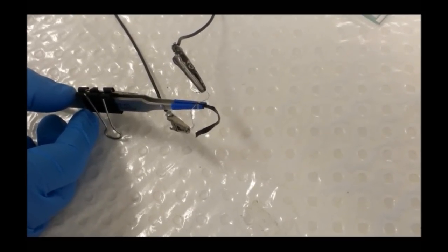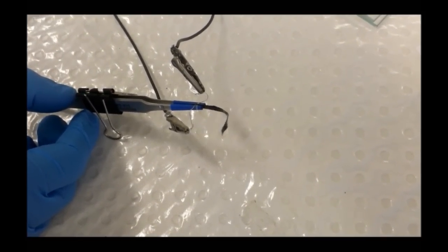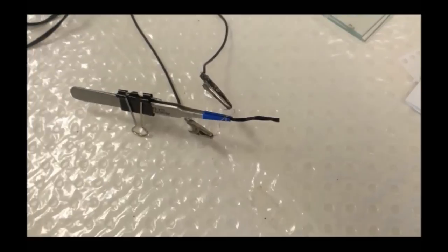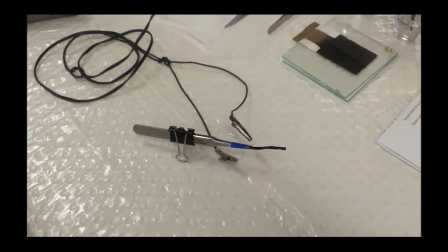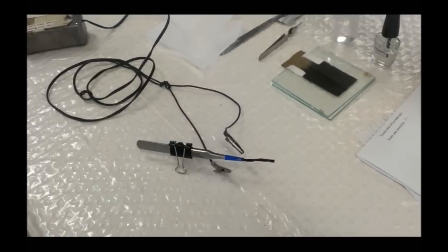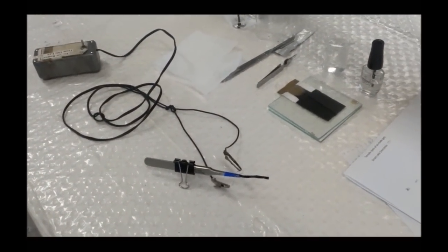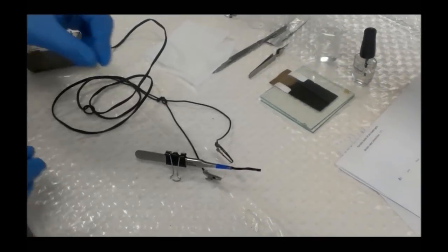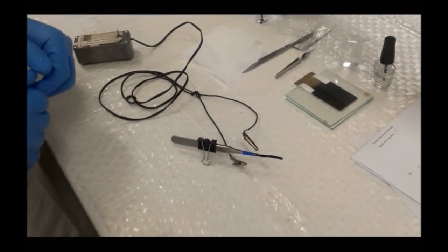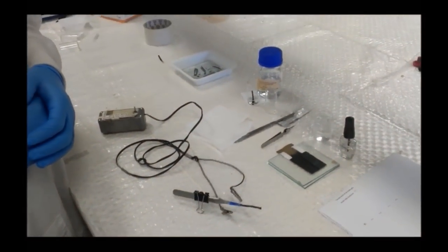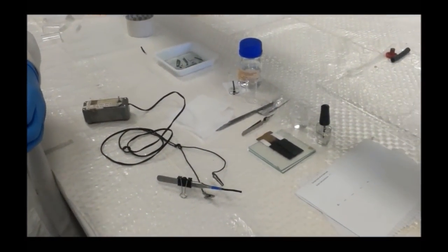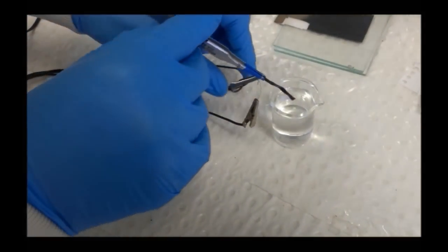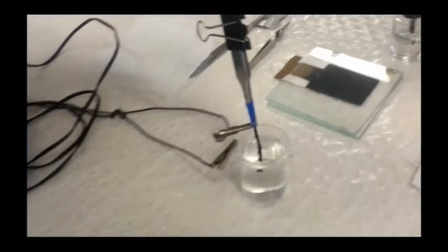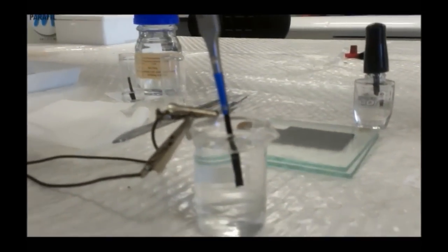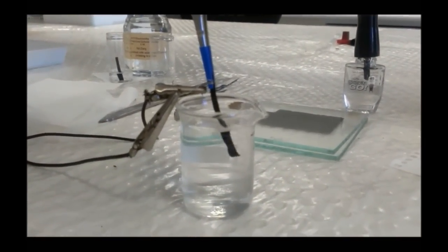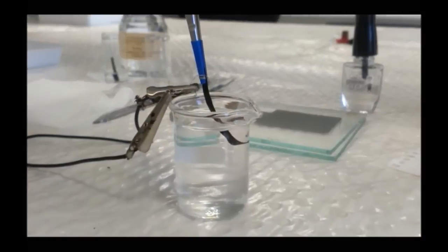Now there's a trade-off between how thick to make the coating. The trade-off is that the thicker the coating, the longer it will last, but the smaller and slower will be the tip displacement. Well, once this is dry, we can then put it in the water and see how it performs in a water solution. Now I will just put the actuator into some tap water. And let's see if it still works. Yeah, still moving quite adequately.